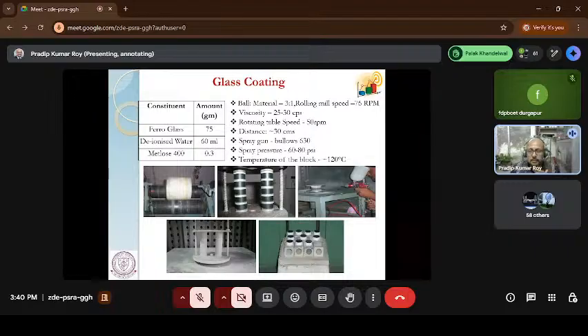So they started with working on the glass composition. This glass is a very low melting compound, made of low melting oxides. Normally glass contains either boron oxide or lead oxide. Lead oxide is very low temperature, but lead again is banned in the market. So this glass was made with boron oxide content, and it was matured at 500 degrees Celsius.